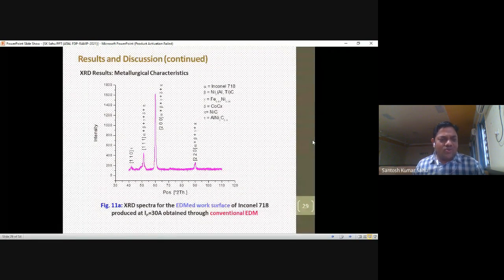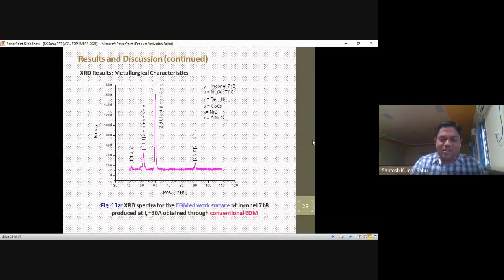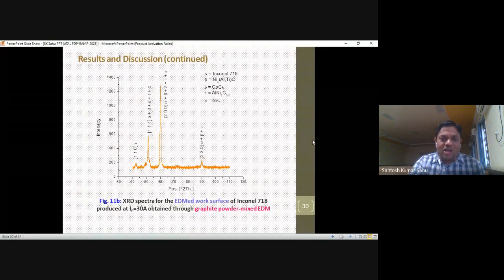The extent of grain refinement taking place during the EDM operation was also understood by comparing the peak patterns, as shown in the figure, of the machined surface compared to the received parent material. So here we can see the peaks of your parent material, and here we see the XRD spectra of the EDM work surface. One is your received work surface, another is your EDM work surface by adding the graphite powder.